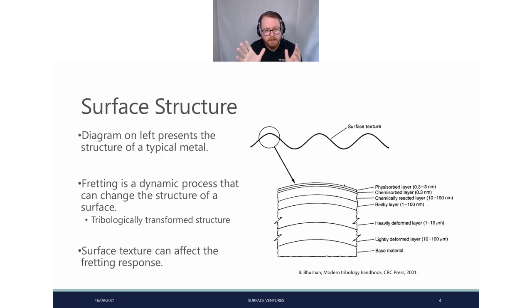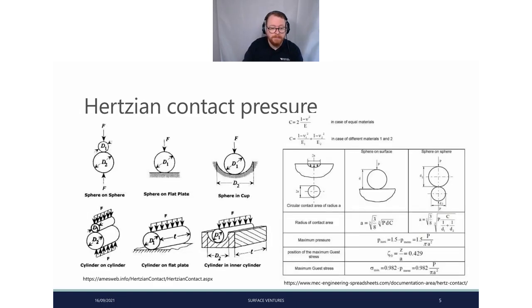One thing to keep in mind is this is our standard model of a metal surface, but fretting does change this. Of course, with more traditional types of wear, like sliding wear, pin on disc, that changes the material as well, but it tends to be less responsive to the actual wear process. Fretting itself has a lot of feedback and interconnected elements. And since I bring up surface texture, this can affect the fretting response. Fretting is quite sensitive to surface roughness.